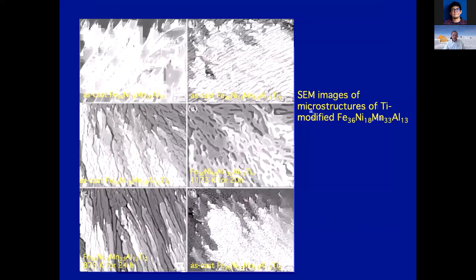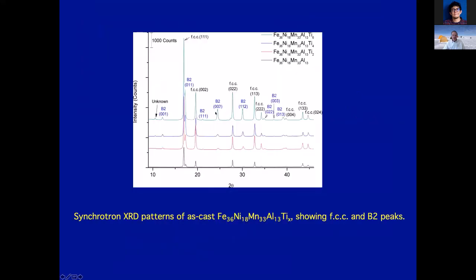So we've also looked at modifying the microstructure by adding different materials. So one thing we did was add titanium. This is material without titanium. Once we added the titanium, we ended up with a much finer microstructure, as seen here in these scanning electron micrographs. But if we actually look at the X-ray diffraction, we've still simply got FCC and B2 phases in all cases.